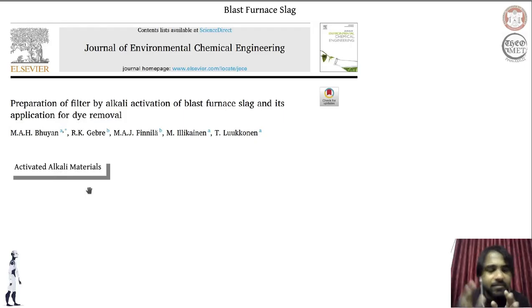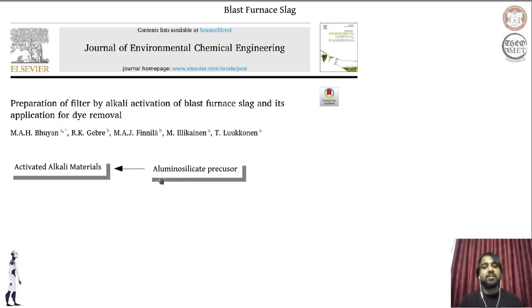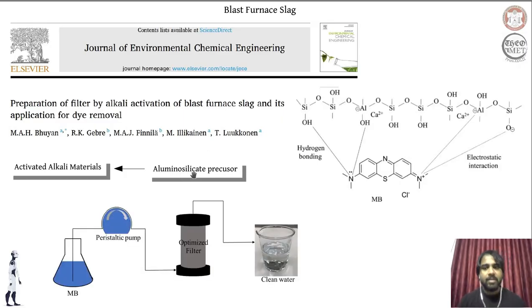Now, to generate these activated alkali materials, we are using blast furnace slag because of its chemical composition, which we have seen in the previous session. Because this blast furnace slag is also an alkaline material, we are using it as the source for synthesizing this AAM. And of course, this high pH solution remains the same. So this is used as the precursor. Since the blast furnace slag can be viewed as an aluminosilicate precursor for AAMs, to this a high pH solution is introduced in order to activate these alkali materials. Now ultimately, the complex chemical nature of the dye and the chemical groups that are introduced by this treatment allow for cleansing the water contaminated with dye.